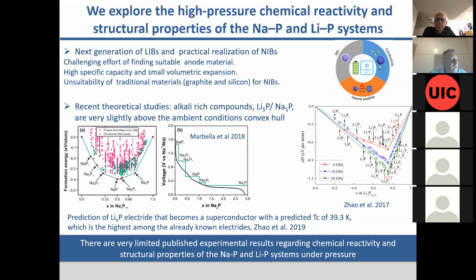In this material, if you see the title of our paper, we tried to be honest. We claim an incompressible material, and the reason was exactly what you mentioned, that we didn't have enough material to perform this kind of study to measure the hardness. And the main reason for that, I think, is that the pressure that we needed to synthesize was so high that you cannot go, at least at that moment, to a large volume press and synthesize enough material to do all this. So I agree with you that it was not a super hard material, it was an incompressible material, and the hardness needs to be examined in the future. Oh, that sounds very promising though.